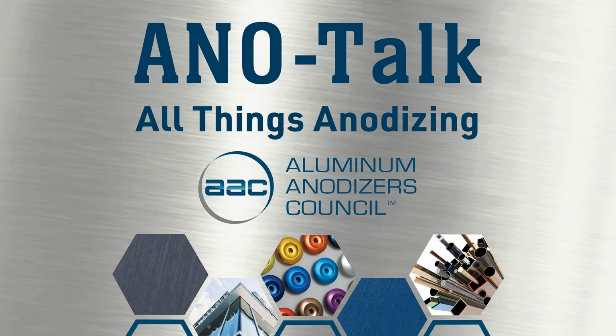So you create an oxide layer from the top to the bottom, you can say, and in that way create the size of the pores, the amount of aluminum oxide, and all these things. So it's really a way to play around, and that is also the reason why it can help you when you have difficult alloys. Also just conventional alloys, which are easy to anodize, because some of them could, by pulse anodizing, increase the efficiency even more, because it's an easy alloy which really can handle, for example, 15 amps per square feet. Sure. Yeah. Okay.